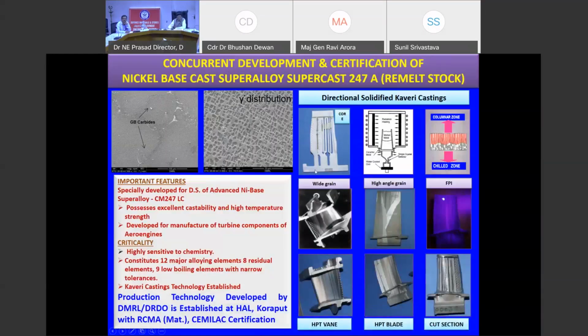So this is a complicated technology. I talked in the morning that Supercast 247A remelt stock. That means it is already melted and remelted. Only by that we can get a compositional control. But still it is an extremely difficult technology because we are looking at a very highly sensitive chemistry without which we cannot get this gamma prime distributions done at a microscopical level. You can imagine each of the precipitate is only a few nanometers to a few hundred nanometers.